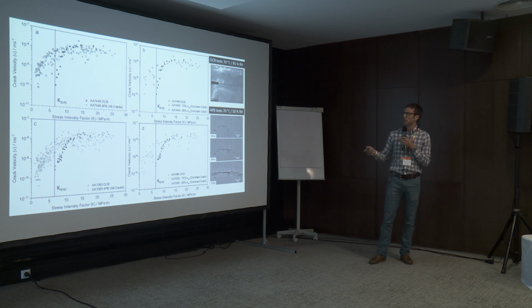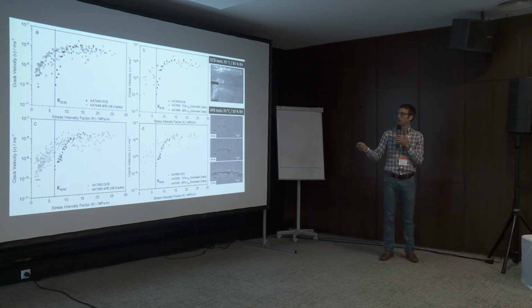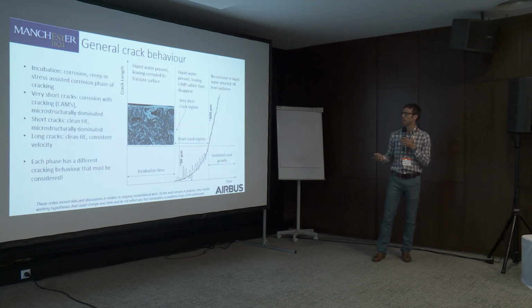and that's the case in all of the samples: we see the cracking starting at very low values of K. Just plotted on the right here are the two dominant cracks for the two different tests at the two different stress levels. And again, we see that the dominant cracks track very much with the upper bound of velocity that you can get for these samples. But that plateau, the maximum velocity they reach, corresponds almost perfectly with the data that we get from the large scale DCB tests.